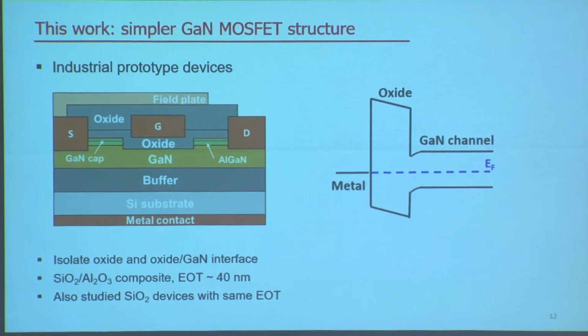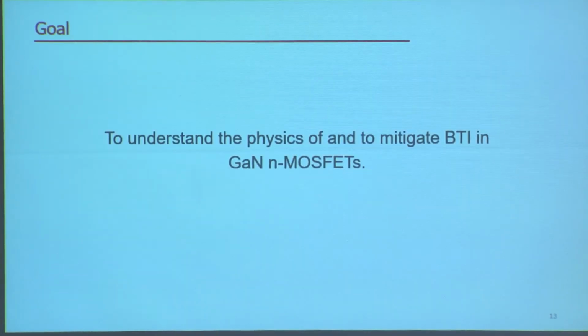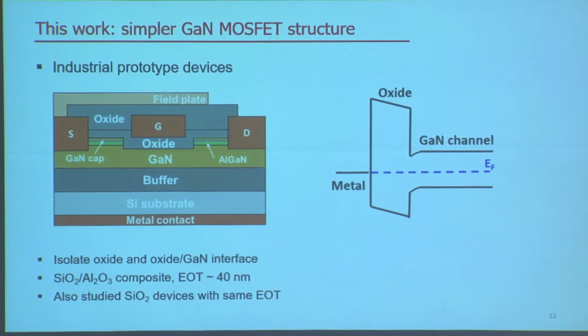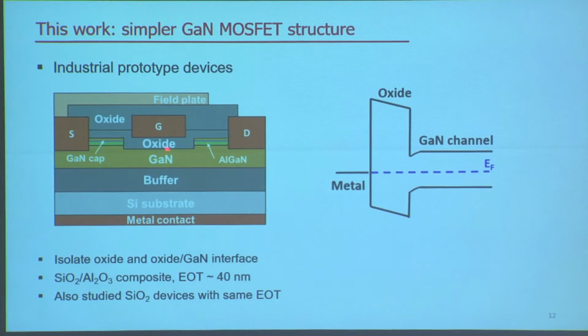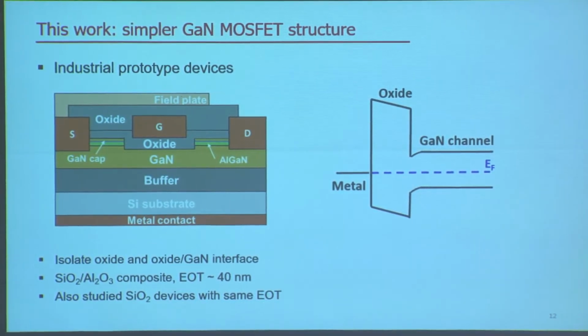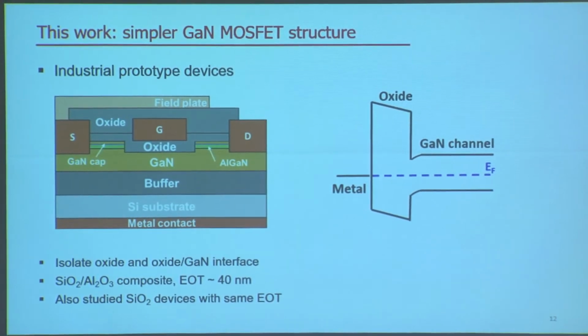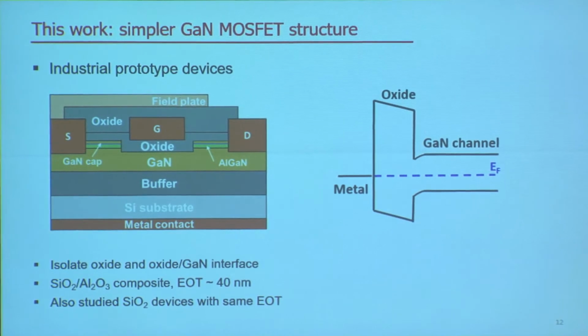So because of that, in our work, we use a simpler gallium nitride MOSFET structure. These are industrial prototype devices featuring a recessed gate. What you see is that underneath the gate, the GaN cap and the AlGaN layer are etched away. So this gives us the opportunity to isolate the oxide and the oxide-gallium nitride interface and study their contribution to BTI.